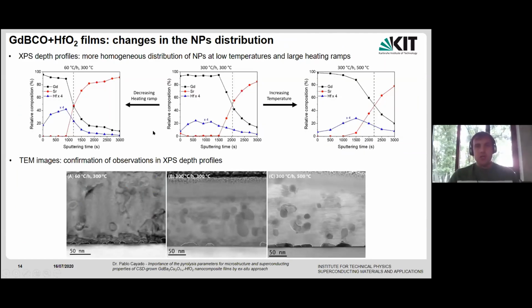This is exactly what I am showing here. We did some so-called XPS depth profiles, which means that we are bombarding the films with ions, and then we are analyzing with XPS the emitted atoms. We see that changing, for example, the heating ramp, modifying from 300 degrees per hour to 60 degrees per hour, or changing the temperature, increasing it from 300 to 500, we observe a change in the distribution of the hafnium signal in this case.